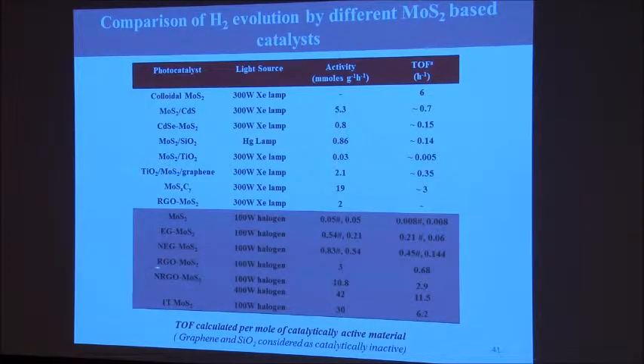However, when you heavily nitrogenate graphene, the one we did, we got a very large amount of nitrogen. But you don't need to do that. You just take the new polytype of molybdenum sulfide, and even with a 100-watt lamp, we get an enormous amount of hydrogen. This is worth exploring.